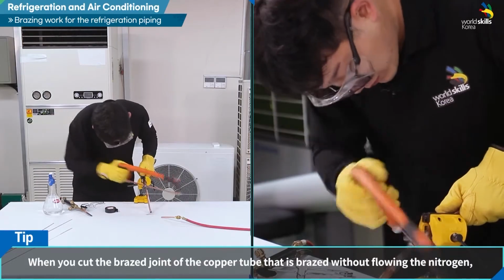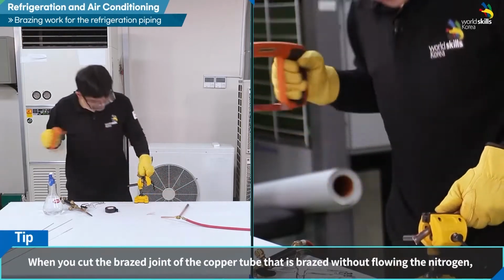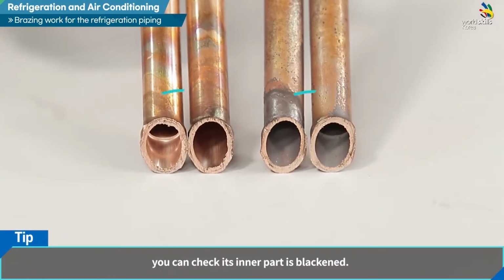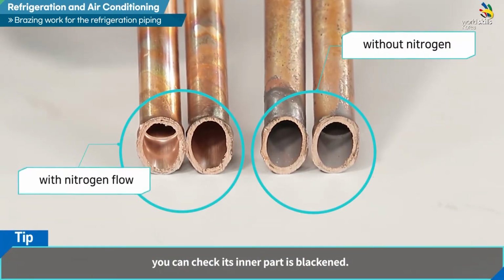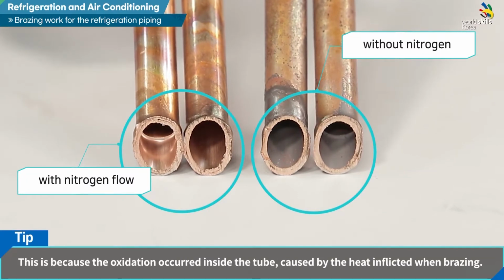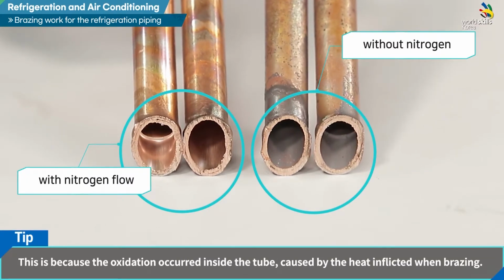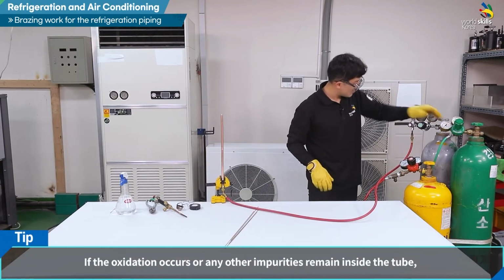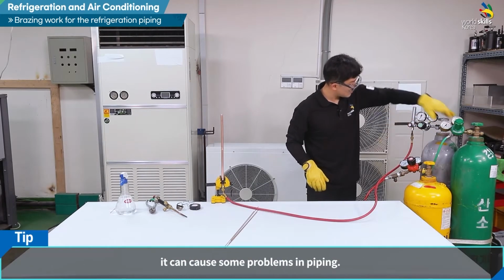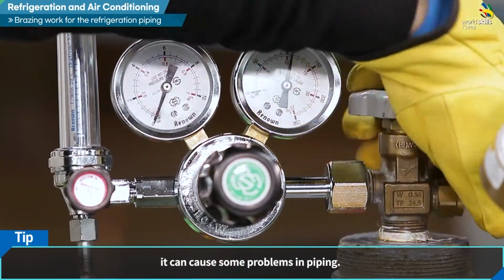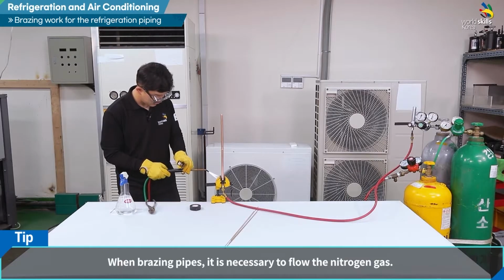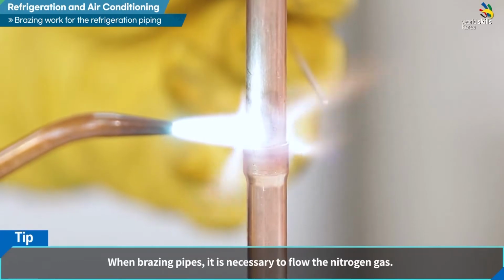When you cut the brazed joint of the copper tube that is brazed without flowing the nitrogen gas, you can check its inner part is blackened. This is because the oxidation occurred inside the tube caused by the heat inflicted when brazing. If the oxidation occurs or any other impurities remain inside the tube, it can cause some problems in piping. When brazing pipes, it is necessary to flow the nitrogen gas.